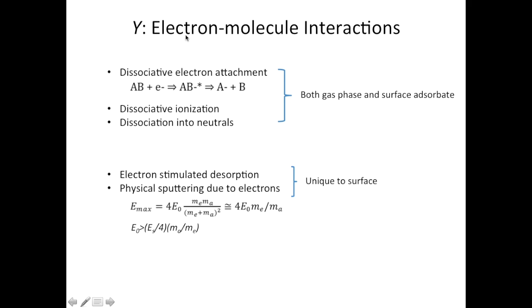The second parameter is the yield, which is related to the electron-molecule interactions. There are all kinds of interactions between electrons and molecules, but here we'll focus on two types. The first type applies for both gas phase reactions and surface adsorbed reactions with electrons, and contributes to thin-film deposition. Dissociative electron attachment, dissociative ionization, and dissociation into neutrals share a similar nature — they all involve excitation of the reactant molecule to a higher energy state, followed by decomposition into final products or radicals. The only difference is that the final products are different: some are cations, anions, or neutrals.